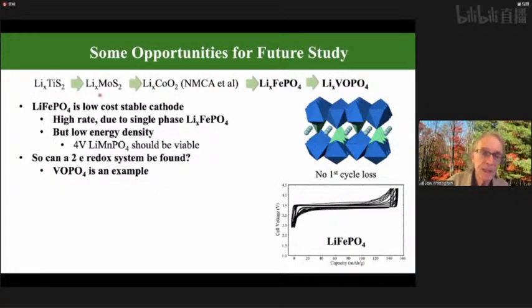I've talked about TiS2. The folks in Vancouver, Moli Energy, looked at molybdenum disulfide in the 80s extensively, talked about that already. Lithium iron phosphate, I mentioned, was of interest for storage, and it was used for grid storage maybe 10 years ago. It's gone out of favor in the US at the moment. It's a one-dimensional structure, no first cycle loss. So again, a clue that we can solve it. But the energy density is really too low for any portable application.